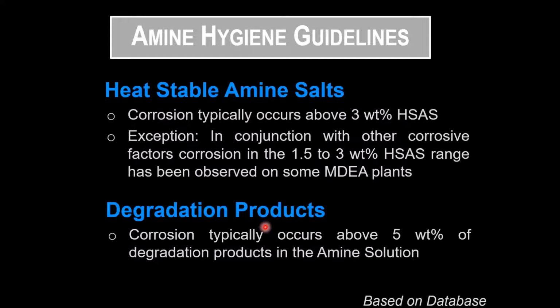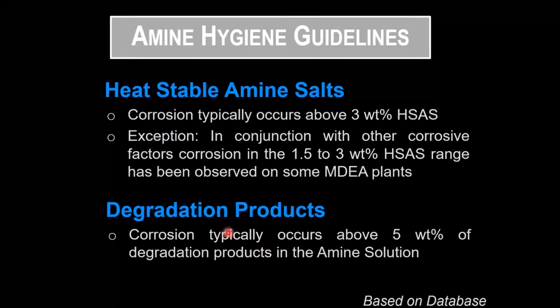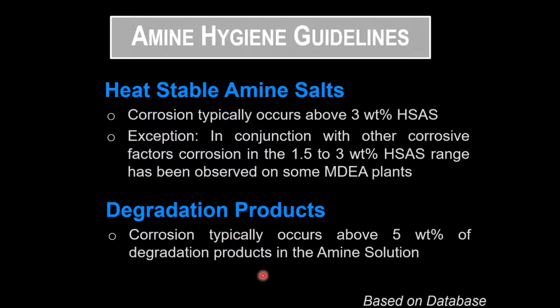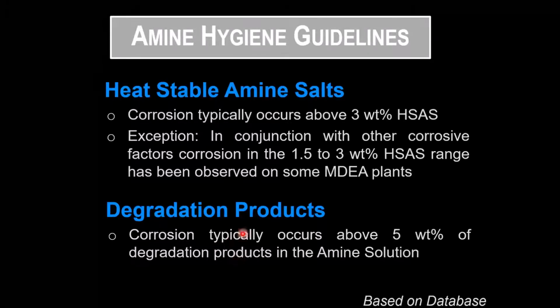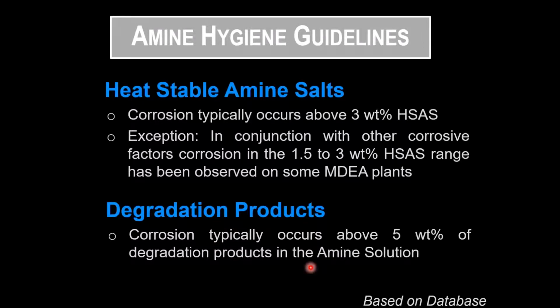Primarily in gas plants, we're dealing with degradation, and the degradation pathway is CO2 attack. H2S does not degrade an amine, CO2 degrades an amine. So the more CO2 you process, the more likely you are to degrade the solution.